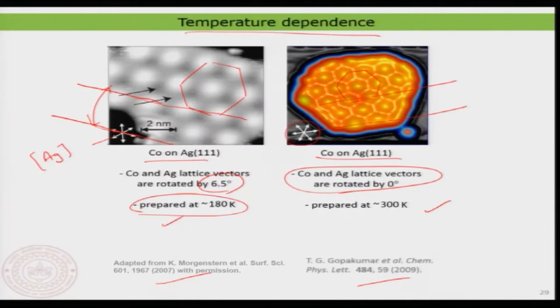What is the difference is that in this particular example, everything is prepared at 300 Kelvin, that means at room temperature, and in this particular example everything is done at 180 Kelvin. That means while you deposit the atoms, the surface is actually kept at a very cold temperature, 180 Kelvin. It is way below the room temperature. And on the cold surface, these atoms are deposited, and then you allow the atoms to arrange and form this nice crystalline pattern. That is quite striking.